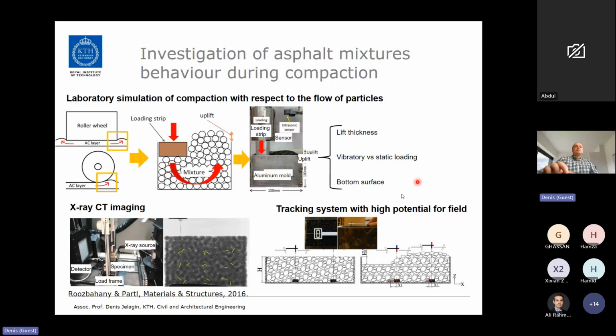Now, this is not exactly what happens in the field. Of course, we have a compactor wheel here on top, but mixture is not completely constrained from flow outside of this compaction wheel. And the idea with this test method was to kind of simulate the same process in the lab. So we have rectangular container where we have asphalt mixture inside, and we have loading strip applied on top of the material. So here you see this picture of the test setup in the lab.